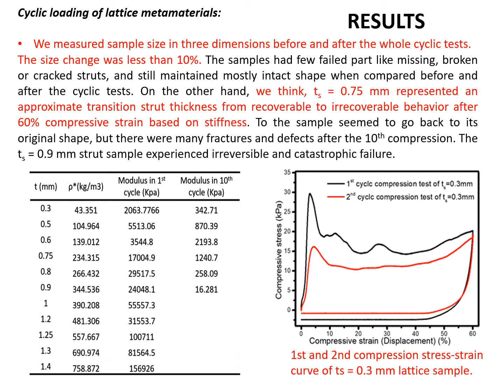The condition that I described related to the yield stress is shown on this graph on the right. You can see that the first cycle of this compressive stress-strain curve has a relatively high yield stress, and then we have additional small peaks. When we go to the second cycle, the yield stress is reduced, and the subsequent peaks have disappeared.